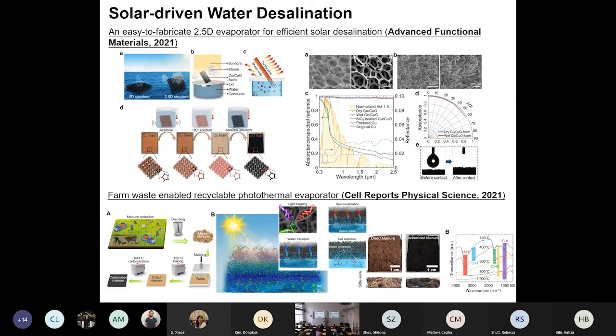So as for the dried manure, after 600 degree carbonization, we obtain totally black. Like I said, I like this color. It means it has really nice solar absorbance, and it can achieve over 95% solar absorbance. For this material, we did not add any chemicals at all. No chemicals. The only thing we need to do is just carbonize it in a vacuum furnace. That's it. And also, we are able to achieve pretty high water evaporation rate. I'm going to show that later, for comparison.